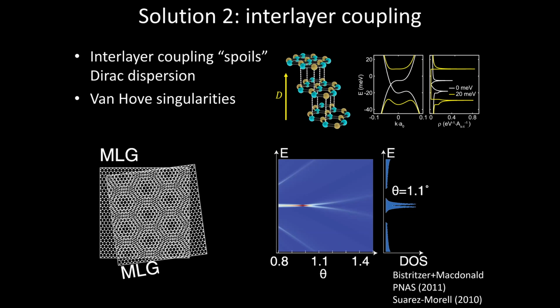The system I'll tell you about today in the first part of the talk is actually a different way to get large density of states, right? Which is to take two graphene monolayers and twist them on top of each other. It's another way to introduce interlayer coupling, right? Which generates a large density of states if you choose the angle just right. So at 1.1 degrees, you'll get a large density of states, and that large density of states is sort of the right situation for interlayer coupling.